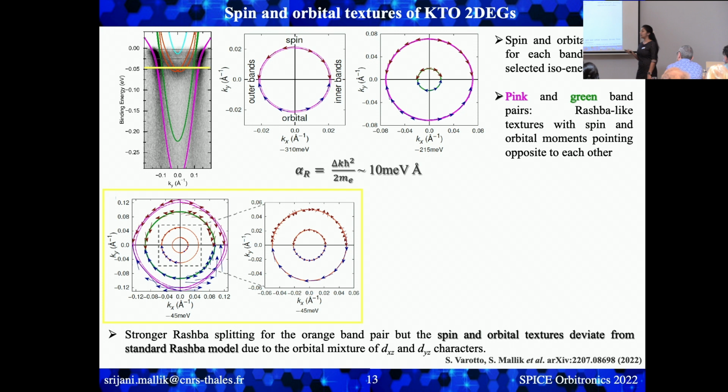So this tells us that although the splitting is quite high, when we calculate the spin Edelstein effect, we probably will not get very high efficiency, because the signs of the spins for dxz and dyz are opposite to each other. So finally they are cancelling out each other, and this is why we are ending up with a very small length of the spins.